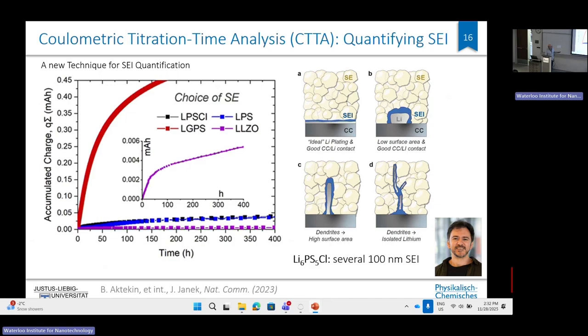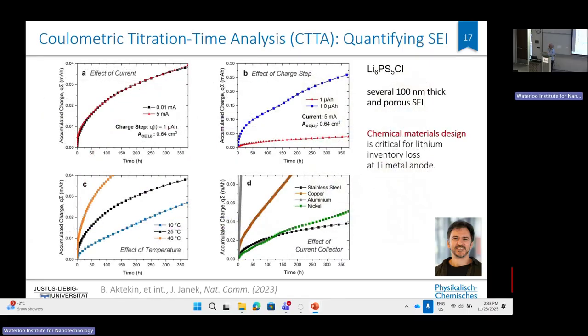So there is an SEI forming, and this SEI is still today, I would say, not 100% understood. What I can say is that this can be designed. You can, of course, modify your solid electrolytes such that they form less, and more stable, SEI, and that's a very important part, I would say, of the long-term stability at the end of any solid electrolyte with your lithium electrode.